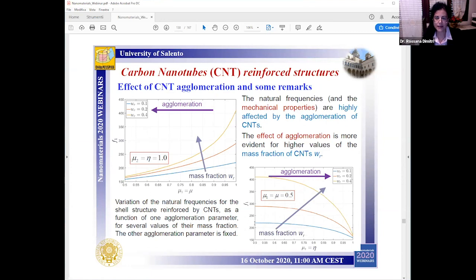That seems to be highly affected by the agglomeration of carbon nanotubes, especially for higher values of the mass fraction of carbon nanotubes. So the vibration frequency, in fact, seems to increase for the increased mass fraction of the carbon nanotubes, where we keep fixed both mu and eta. These results can have, of course, a great impact among scientists, especially for optimization design purposes, both for materials and